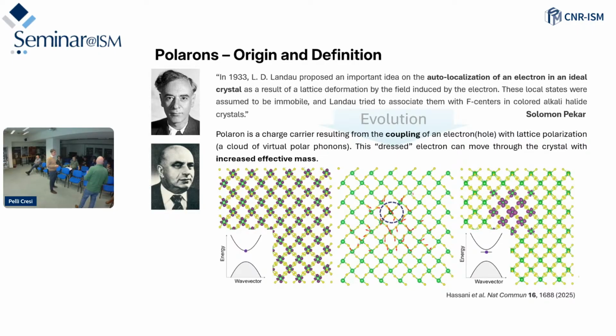In the case, for instance, of cerium, the 4f orbitals are very localized, and when you excite a 4f electron, there is a small perturbation of the environment, of the nearest neighbor sites. I can show you some results of our group, also with Stefano. So no theoretical calculation? No. Starting from calculations from the literature, for the case of cerium we just observe the same energy shift induced by the formation of the polaron. Then you compare with, for instance, DFT calculations? The model is just a linear model.